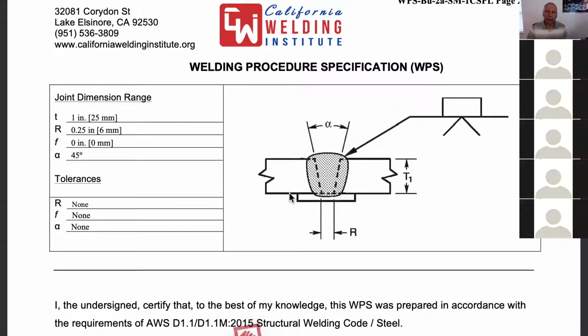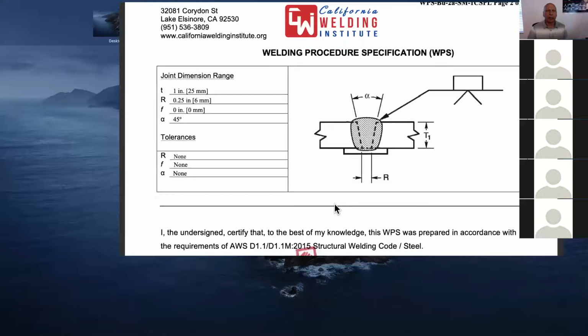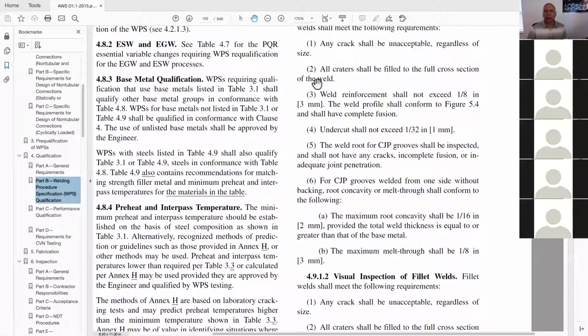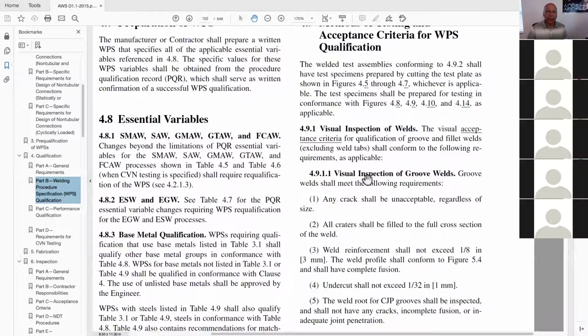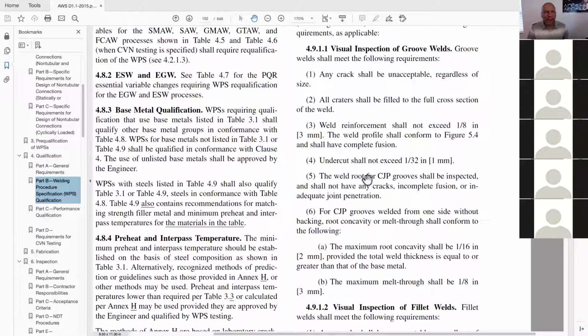If we don't remove that steel backing, we simply did not do our job, and we did not conform to code, because we did not visually inspect in accordance with 4.9. I find that probably 99.99999% of the testing officials out there are not removing the entire backing and grinding the backside smooth to inspect the weld root. The weld root is not the root bead; there's a difference, and you can go to AWS A3.0 for the definition. It clearly tells you the weld root is on the root side, on the back side of the joint. In a double welded joint, it is in the center. With a weld root, you would have to inspect it from the second side.